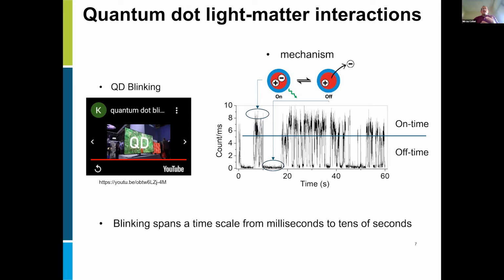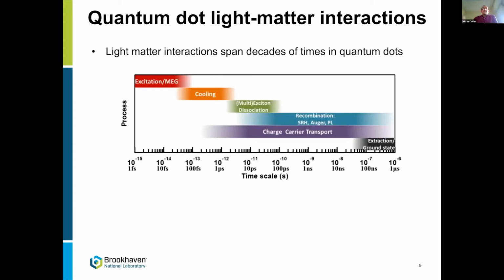So what we want to say is that this blinking for a single quantum dot or a few quantum dots spans the time scale from milliseconds to tens of seconds. So it's really a process that goes over a couple of decades. But if we look deeper into the quantum dot light-matter interaction, we find out that besides the blinking, there is a variety of processes that a quantum dot can undergo. I'm not going to recite all these processes. What I want to stress here is the time scale that these processes go over, from femtosecond all the way to microsecond. And now we add the blinking, which is millisecond to second and tens of seconds time scale. So we really have decades of time for processes going on in quantum dots.